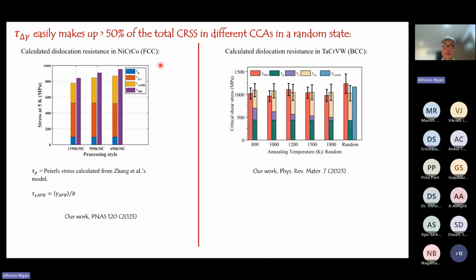No matter what system we are looking at, that contribution due to the fluctuating gamma turns out to be the dominating component compared with, for example, the Labusch-type strengthening or what we call the Fisher strengthening due to the breakage of the ordering. In this case, the red color will be what we're looking at. In this FCC system, that will be like 60% at least. And for the BCC system, we'll be looking at this beige color, which again is the dominating component, especially for the random state.